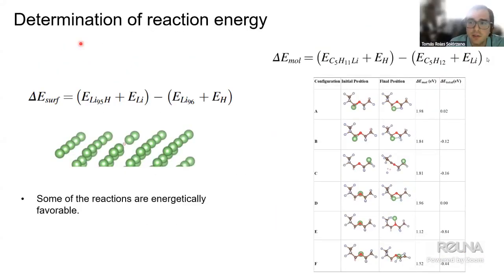Later on, what we did was try to map the reactions as a whole. So we took out one of the protons, or a hydrogen atom, from the molecule. We attach a lithium, which will be the reaction you would expect from a system like that. And we calculate the energies before and after, or the change in energy after you remove the hydrogen and attach the lithium. That will give us this energy over here. We also calculate the energy of a single, isolated hydrogen atom. On the other side, we also calculate the molecule in a pristine way and the molecule on the lithium surface.